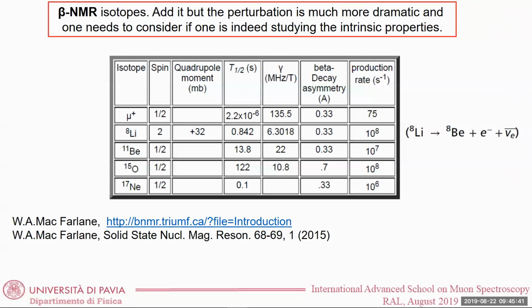You mean the number of lithium nuclei you produce per second? It's 10 to the 5, roughly, per pulse, or 10 to the 6, depending. You can either pulse it and then look at the SLR, so you can do it without RF and look at T1, or you can implant continuously. You can also implant continuously and do an RF experiment, radiating with the frequencies to map out the splittings. So you are always ultra dilute; you never have interactions between lithium nuclei.